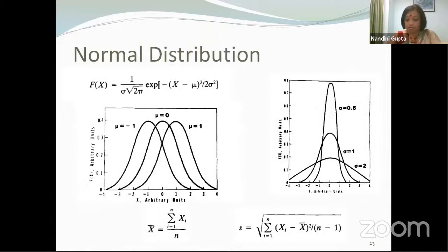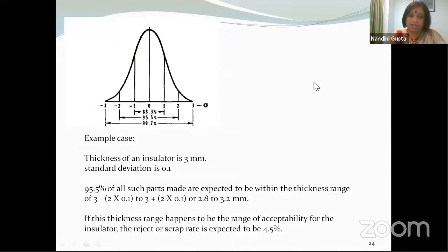Obviously, the material that you would choose is the one with the smallest standard deviation, because even though, let's say, they all have the same breakdown strength, in case of the material with sigma equal to 0.5, you have more reason to rely on that data, because in this material, most of the breakdown will happen near about that particular value. Whereas in the material with standard deviation sigma equal to 2, you would have many breakdowns at values far away, much higher or much lower than your mean value. This unpredictability is not something that is desirable in engineering.